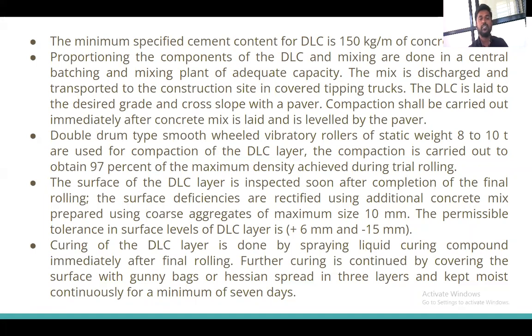Then the surface of the DLC layer is inspected soon after the completion of the final rolling. After the rolling, we have to confirm whether the DLC layer surface is good enough for applying the PQC. Also, we have to see the tolerance limits for the surface layer. Leveling of the surface layer should be done within a tolerance limit of +6 or -15 mm. That is to be achieved on the DLC layer.